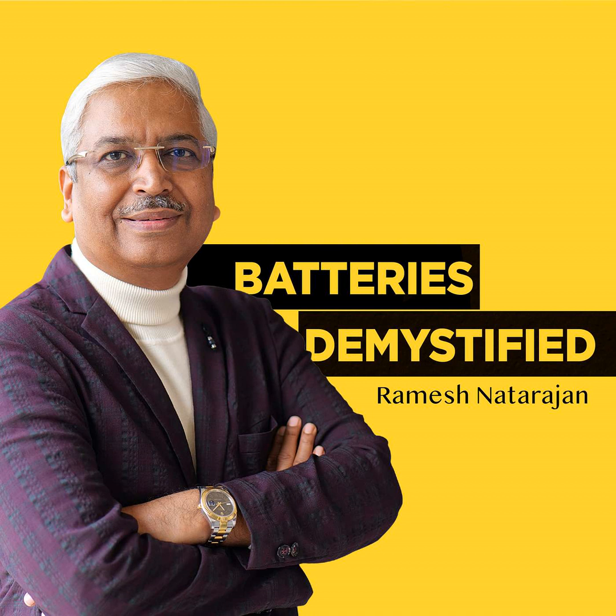That really gets to the cutting edge of what we're trying to understand in battery science right now. One of our research priorities is to identify where the lignosulfonate goes and how it functions when it's actually in the battery. One concept we're working to explore further is whether we have dissolution of the lignosulfonate from the negative electrode into the electrolyte, and if that's where it needs to be to achieve the performance that we're looking for. If that's what's happening, then the solubility in different acid strengths is really a key determining factor. However, we don't really have any evidence that supports this, so it's just a hypothesis. What we do know is that both Vanisperse A and these other lignosulfonates, DCA and HT1, all perform very well. So it's really difficult to say whether it's an advantage or not.